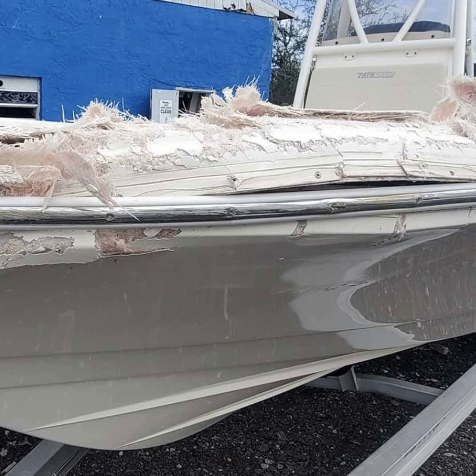You now have your resin catalyzed, and you're always going to start with chop strand mat, in my opinion. You don't want to go straight to anything woven, even though it has some chop strand on the back of it. If you're just starting your lamination onto a repair, you want to start with at least one layer of 3/4 ounce or 1.5 ounce chop strand mat. Some repairs, you can build the whole thing up with chop strand mat. Sometimes you might put a layer of 1.5 ounce down, and then a few layers of 1708. You get a little structural repair going on.